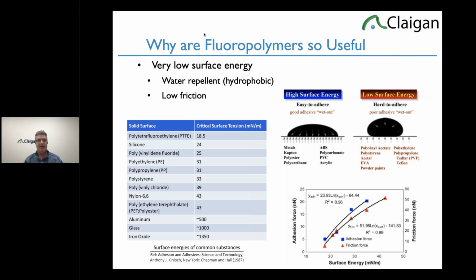That's why, if you grind down on your brakes to metal on metal, it's spectacular because they're really high friction. You can look at the metal ones, the glass down the bottom, super high friction, as opposed to silicone and PTFE, which are very low. Silicone's downside is it's quite water repellent, but it's unbelievably poor at repelling oils. It means you get stains, you get smells. If you have silicone cookware, you're probably used to it sucking up smells and flavors. It's because silicone is not resistant to oil whatsoever, while PTFE is.